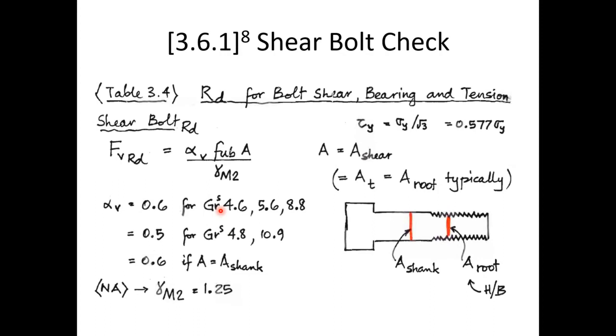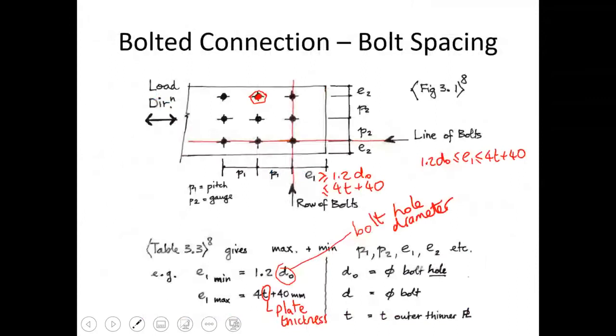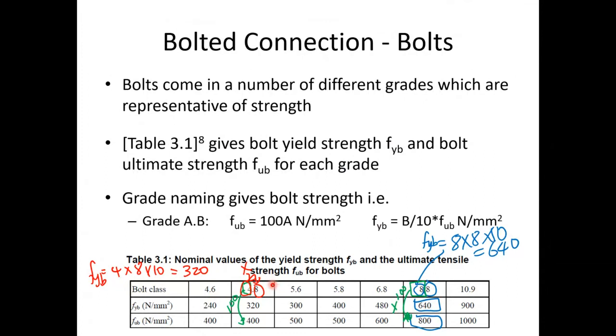So why is there a different value? Let's just go back and look at them. If we look at this table here, comparing 4.6 to 4.8, you can see the difference between the yield strength and the ultimate strength for 4.6 is 240 for the yield compared to 400 for the ultimate. There's a 160 difference. But if we look at 4.8, the difference between the yield and the ultimate is very close, 320 compared to 400. Same thing if we compare 8.8 to 10.9. 8.8 is 640 compared to 800, so it's about 160 of a difference from the yield to the ultimate strength, whereas 10.9 is only 900 compared to 1,000.